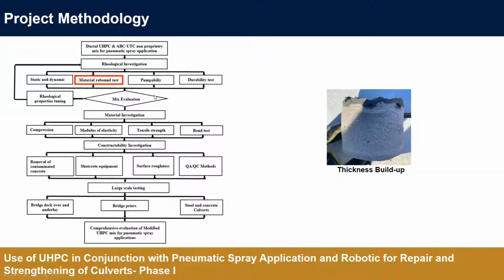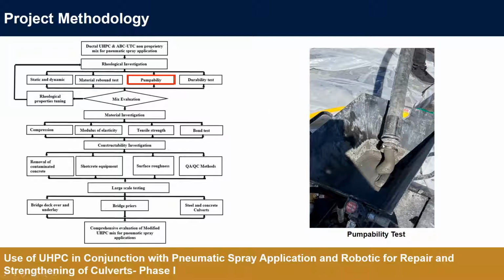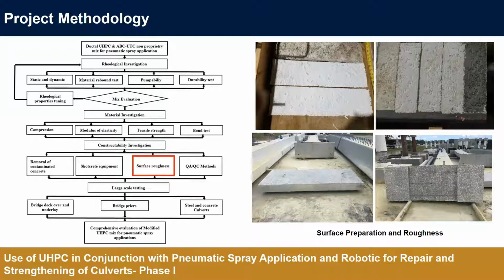Here, related to material rebound, is the buildup thickness. You can see here we have some cores taken from a shot material specimen, and you can see in the gray on top how much, about a half inch, of buildup in this specimen. We also conduct some pumpability testing, and you can see here the flow of the material. This material was without fiber, but we were able to shoot it with fiber too. Also, surface preparation, as Dr. Azizinamini mentioned in the last presentation, sometimes we do sandblasting, but in this project we also use different membrane skins with different amplitudes of roughness to measure different roughness conditions.